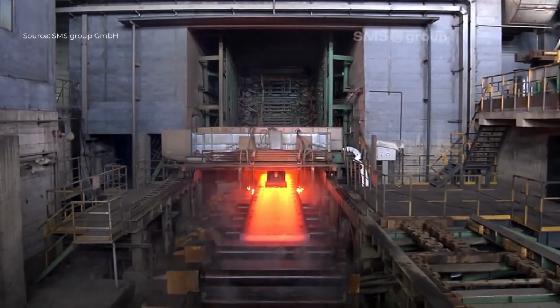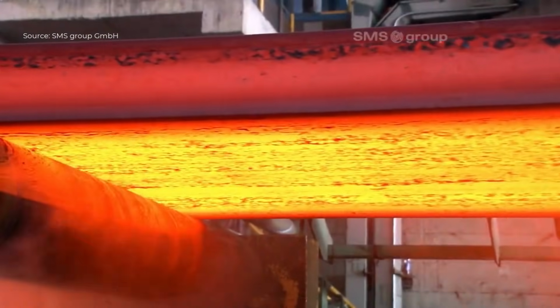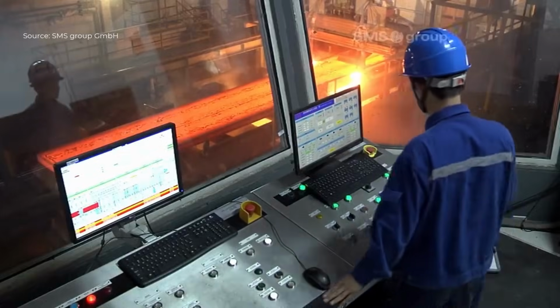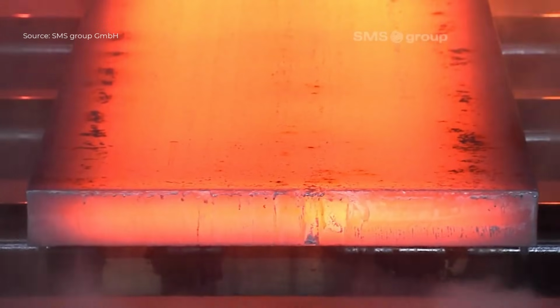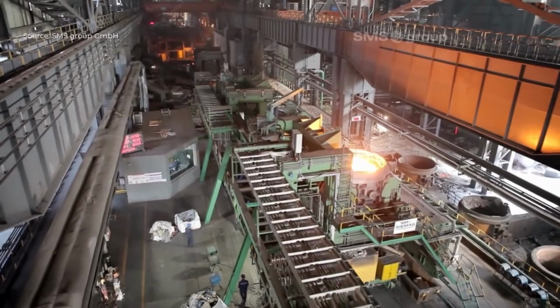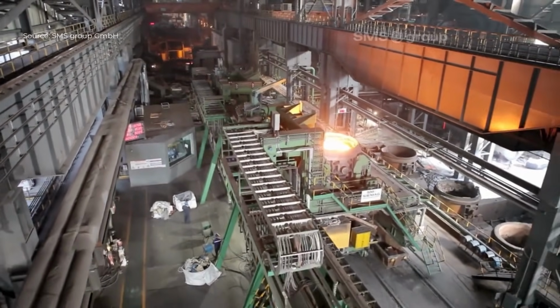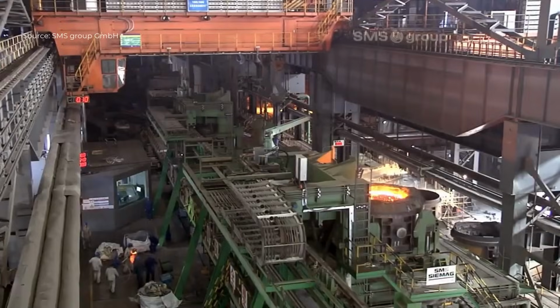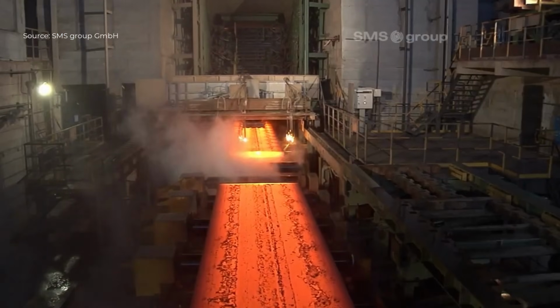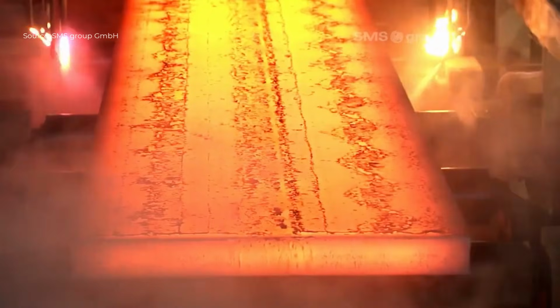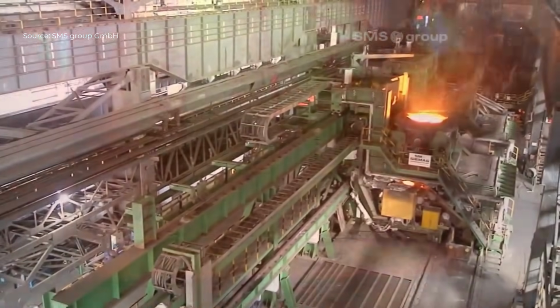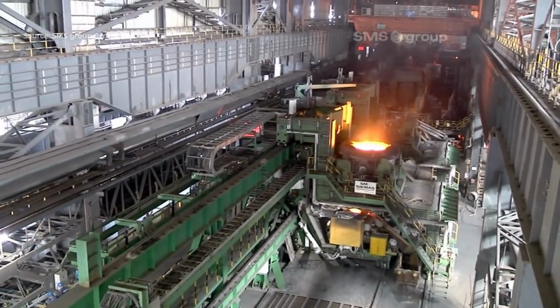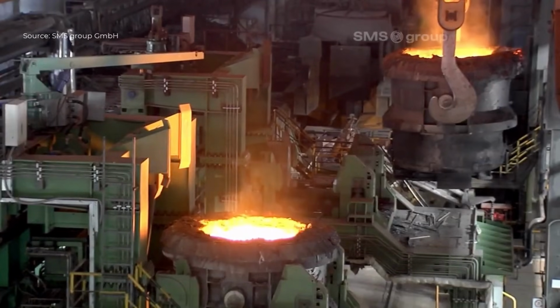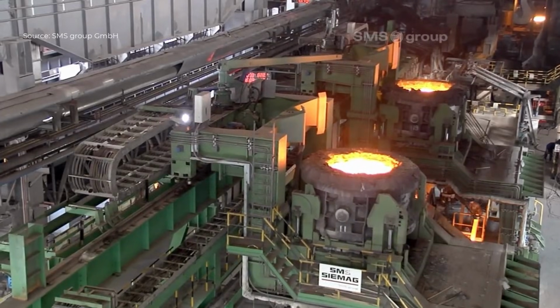When the partially solidified strand exits the mold, it enters the strand guide system consisting of 8 precisely aligned segments. This system supports the strand, maintains its geometry, and guides it smoothly along the casting arc. At this stage, secondary cooling is applied through an integrated air mist cooling system. By using a controlled mixture of air and water, the system achieves uniform heat extraction, ensuring stable cooling rates and preventing surface or internal defects. This controlled cooling promotes high steel cleanliness and the formation of a homogeneous internal microstructure throughout the slab.